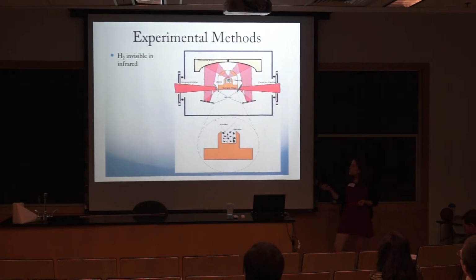We mainly use infrared spectroscopy, and if you know anything about hydrogen and infrared spectroscopy, you know that no one ever does hydrogen with infrared spectroscopy. Hydrogen has no dipole moment, so the charge is uniformly distributed, so you never see it. But when we put the hydrogen into the MOF, it induces a dipole moment, so it sloshes the charge over to one side, basically, and then we can see it in the infrared. So this is actually a feature of what we do rather than a problem, because we can only see the gas that sticks to the MOF, and we're not confused by everything that's not sticking, things that are in gas phase versus adsorbed phase.